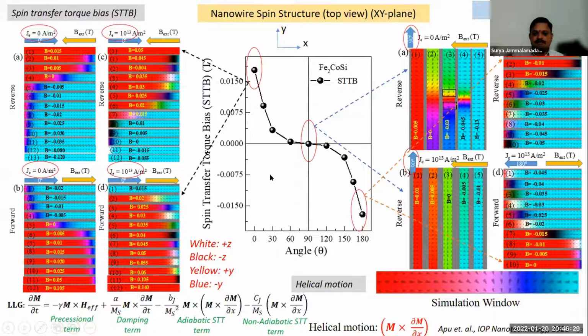To understand this phenomenon, as I mentioned, by changing the angle between the magnetic field and the length of the wire and sending the spin polarized current, we do see a shift of the hysteresis loop, and we tried to calculate the exchange bias value at zero angle. We do see very high spin transfer torque bias, and at 180 degrees, the spin transfer torque bias is also very high. At 90 degrees, we don't see any spin transfer torque bias.